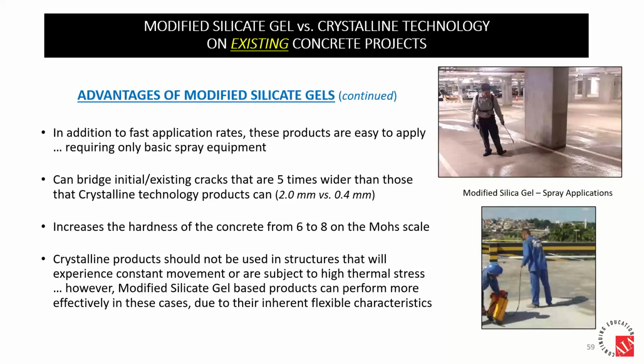But specifically with the modified silicate gel, on initial installation, they will actually heal a crack up to 2 millimeters wide. And that's a significant crack. That's about like looking at the width of a car key, like the top of a car key. That's much larger. That's 5 times bigger than a crack that the crystalline can heal.